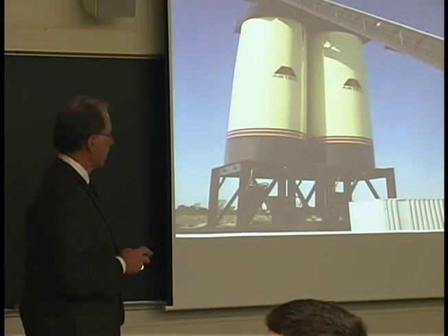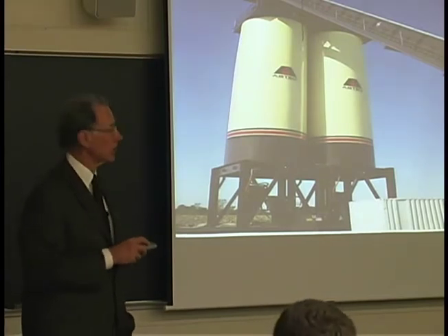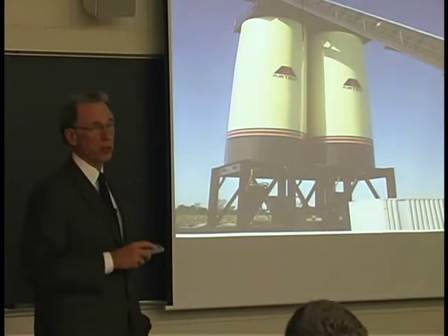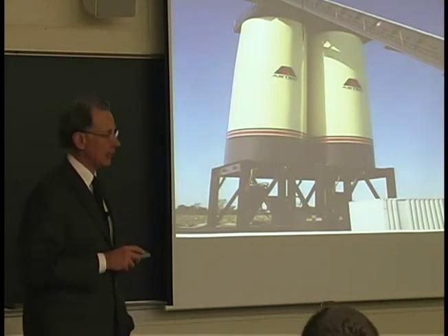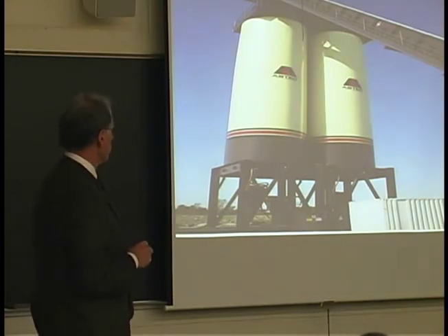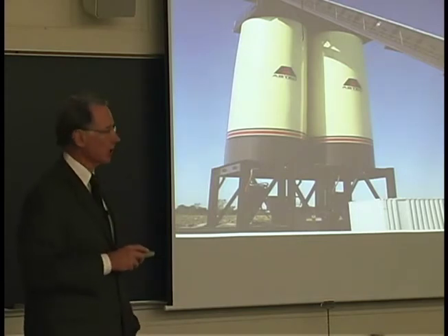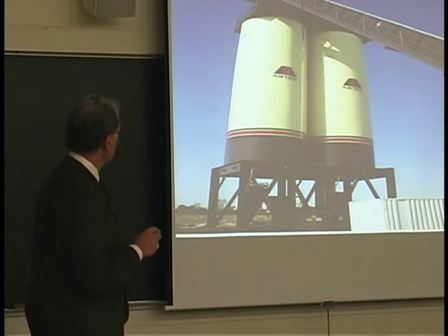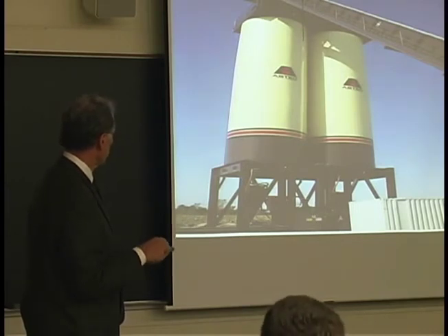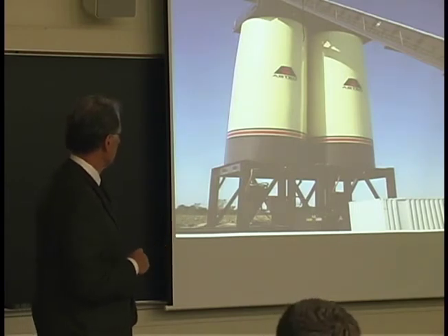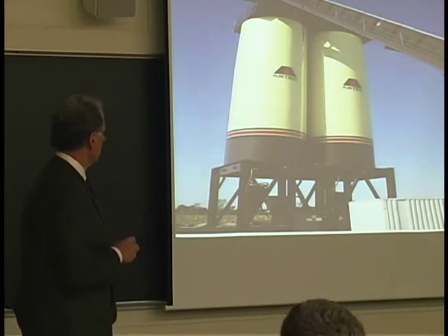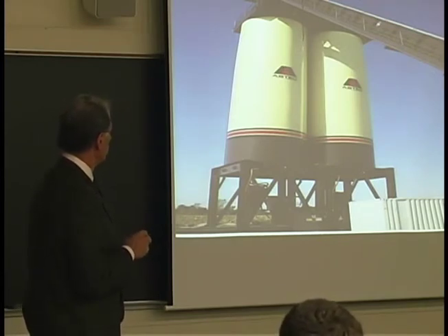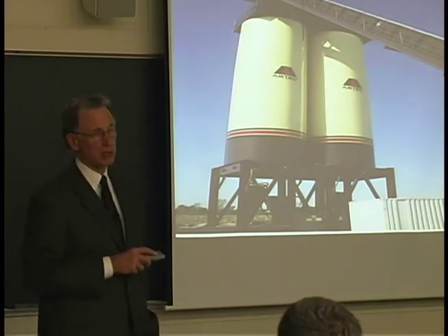The state of Illinois would allow us to keep asphalt in these storage containers for about 24 hours. But most contractors don't like to store asphalt that long. We can store it here if you have a shortage of trucks for a while, before you can stop the process. The trucks will pull under here, and then we can load them quickly and get them out. But by and large, in Illinois, you don't store that asphalt more than a couple hours.